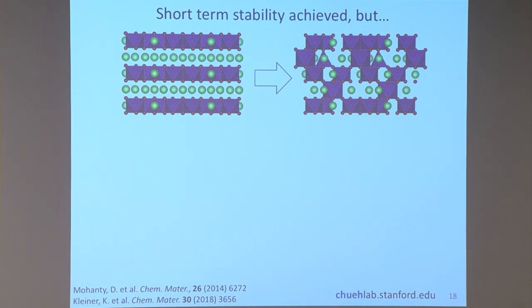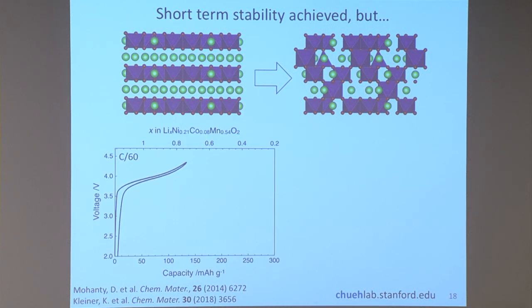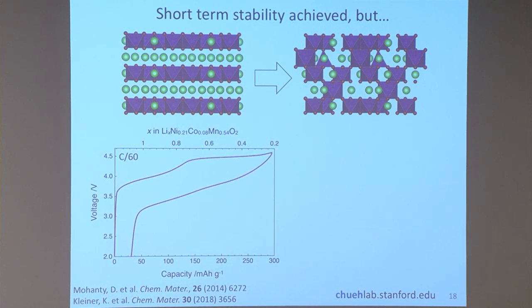Let me show you a couple of interesting performance. This is what happens to the voltage curve of the battery versus the amount of lithium you're inserting and removing. So if you remove about, say, half of the lithium from this material, it's actually very reversible. But the capacity is fairly small. But if you were to charge up the battery all the way, you can double its capacity. But what you get is, you can see the voltage on the way back, it's very, very sluggish. So it becomes very hysteretic.